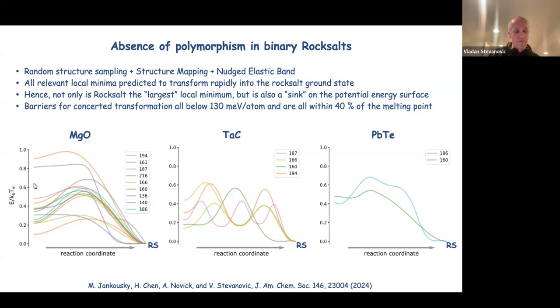In the case of magnesium oxide, we find the largest number of more symmetric, not space group 1, local minima. So these are the space group numbers, and these are the energy profiles of them going into rock salt. On the y-axis now, we divide the energy by the melting point of the rock salt magnesium oxide, just to express everything relative to the melting point so that we can discuss the kinetics a little bit. And what we find is that all the barriers are within, I think for magnesium oxide, around 30% of the melting point. So even with this relatively crude barrier estimation, we find that all statistically, hence more realizable, local minima will transform quickly at typical synthesis temperature into the rock salt.